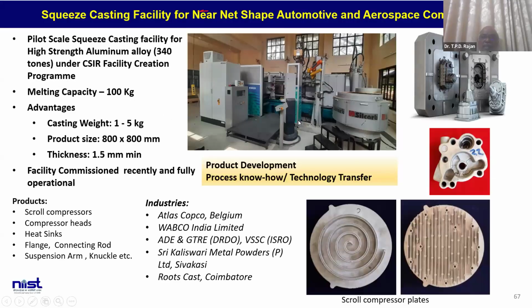In turn, these alloys will have very high strength. The squeeze cast alloys will have almost 385 megapascal tensile strength, but the normal gravity cast has around 270. So those are the advantages. This is a pilot scale squeeze casting facility which we have at CSIR NIIST, where we have a 100 kg melting capacity, and we can melt the metal and pour it into the feeding system. We have an auto ladle system. The metal gets poured, the component is pressed, and it is then ejected.